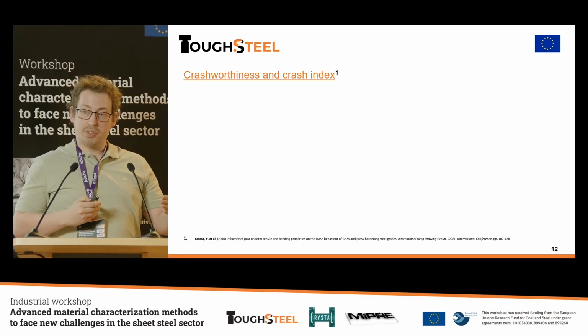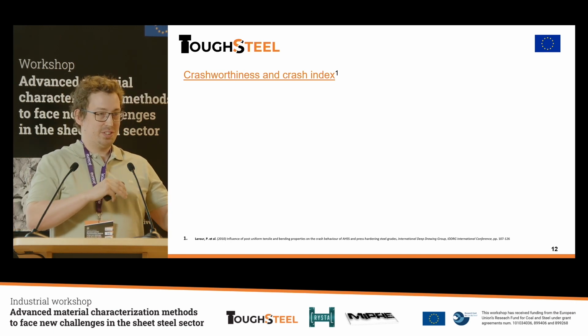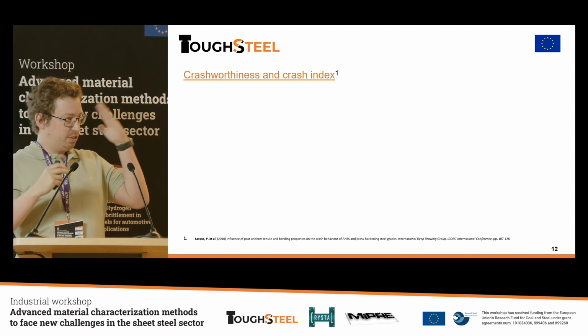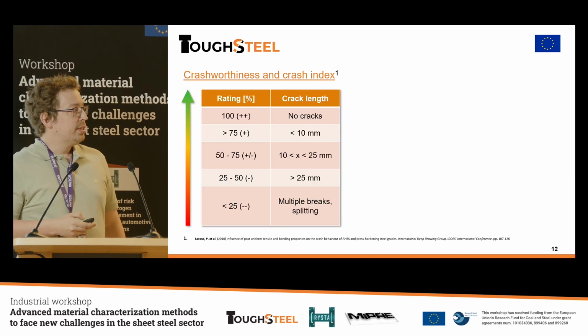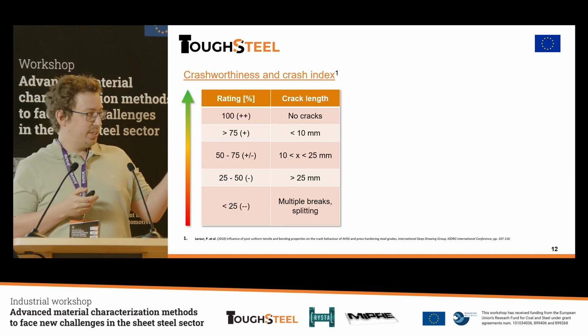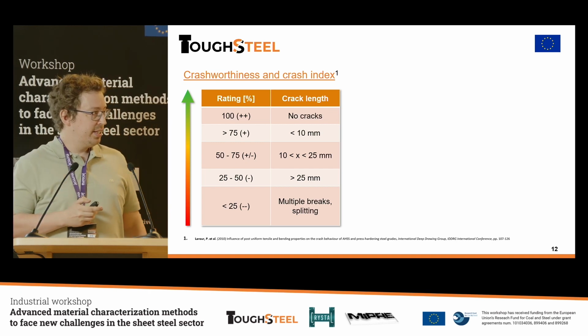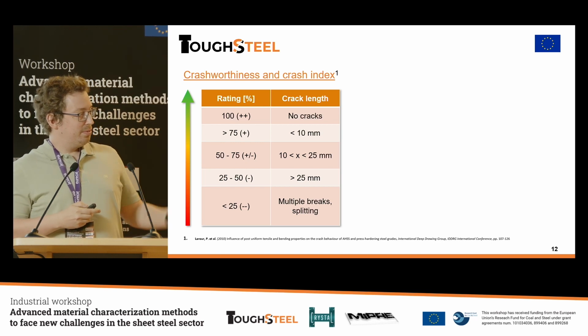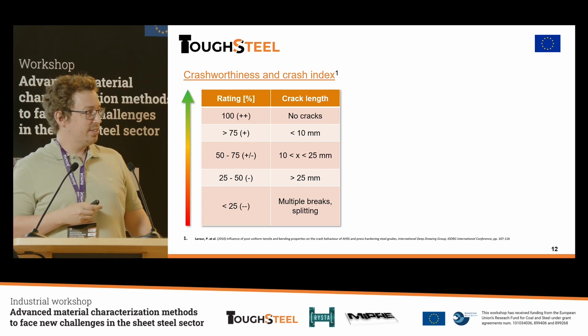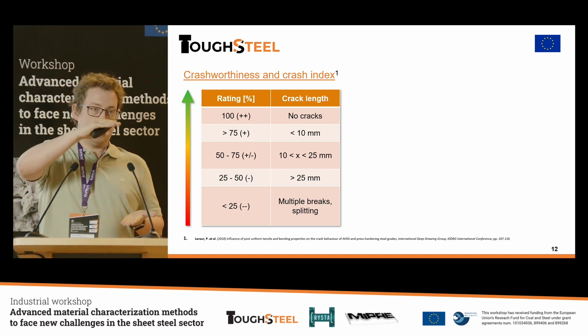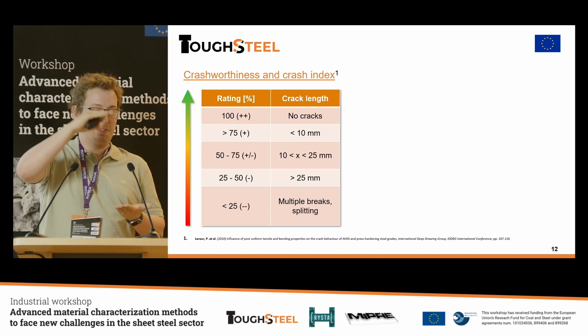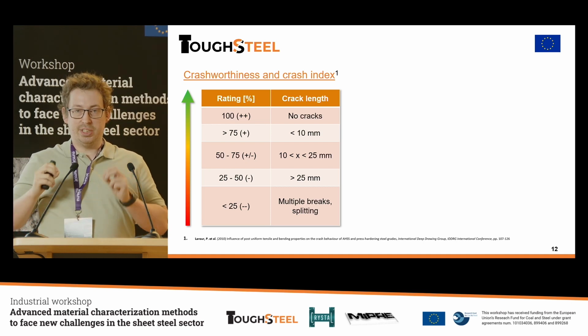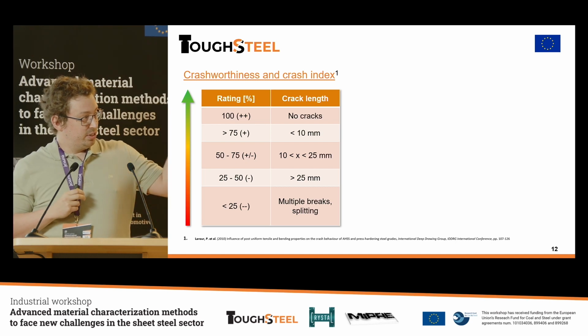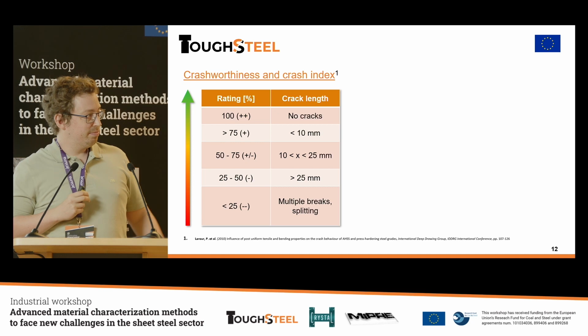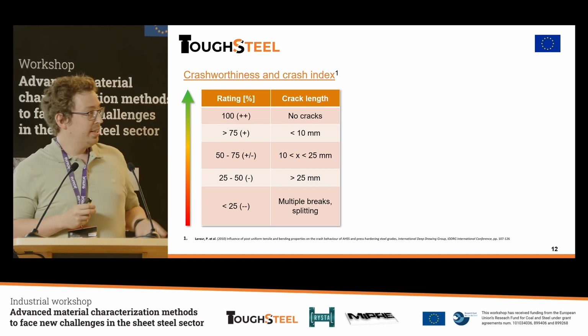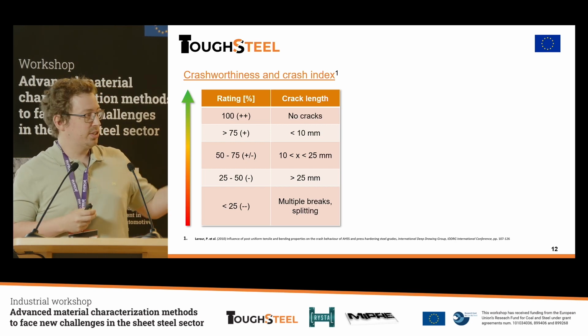And this is usually done with crash boxes, either in the front of the car to absorb the energy when you crash into something, or to protect the passenger cage from intrusion when you're hit from the side, for example. So how do we quantify crashworthiness? I will focus on the compression part of the crash boxes here, and not the side impact. When quantifying crashworthiness in these cases, you can use a crash index. Basically, you crash several different crash boxes at several different crush depths, and you measure the severity of the cracking for each crushing distance. You attach a rating to it depending on the amount of cracking, as you can see here. For example, 100% is no cracks, and 75 is below 10 millimeters, and so forth.